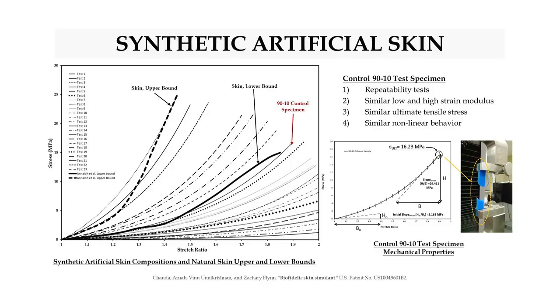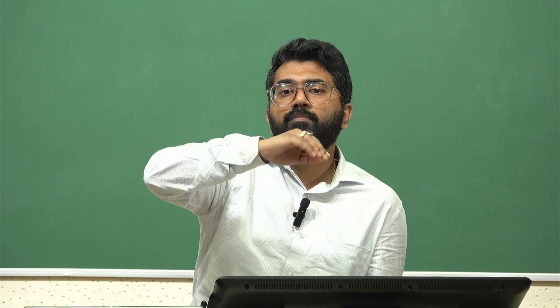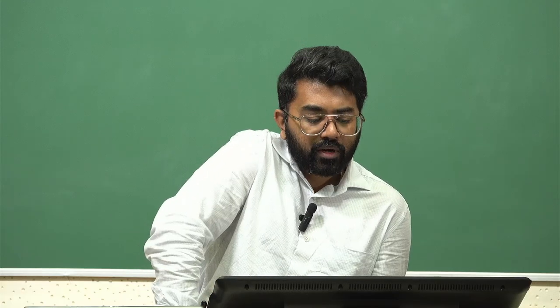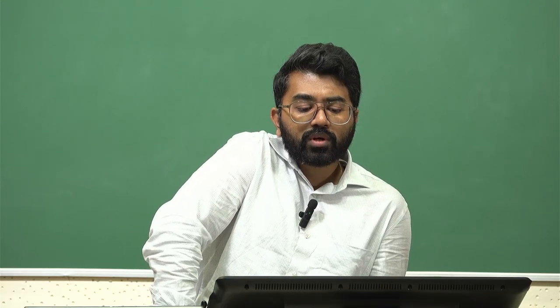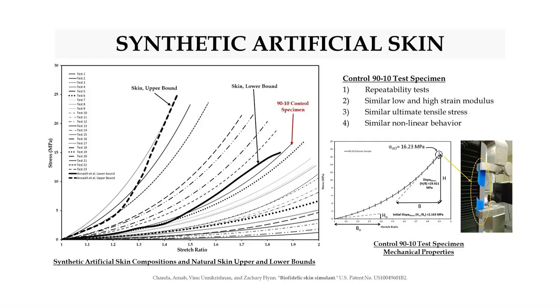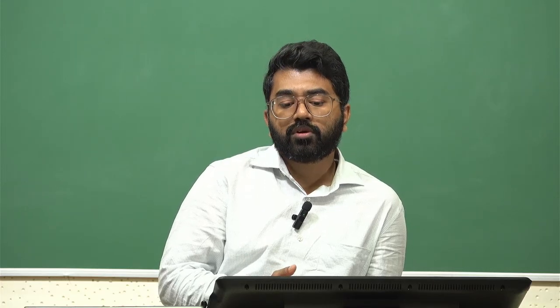So, what we did next was we took the 90-10 control specimen, and we found out that it is closer to the skin lower bound. So, we could consider it as very close to the skin lower bound, and then we repeated the test around 30 times, right? So, we got a lot of stress strain plots for that, but they almost matched, and we could draw an error bar within 5%, right? So, that meant that we had not only created an artificial skin which lies within the range of lower to upper bound, but we had created a repeatable and reproducible artificial skin, which is of importance, right? So, these are some of the terms which we should learn while we are trying to develop soft tissue simulants.